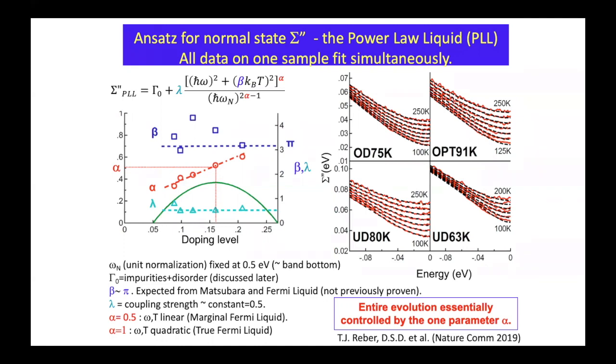Lambda, this coupling thing that says, okay, it's linear in T or something near that, well, how fast does it go linear in T? That's my coupling parameter, lambda. You find that's essentially doping independent, 0.5. And this is basically this Planckian dissipation, but more details on it. This is a very pleasant surprise, this is so constant. And then everything else just comes linear.